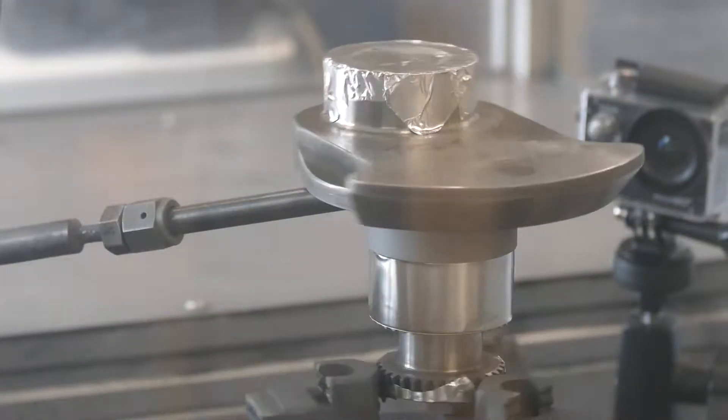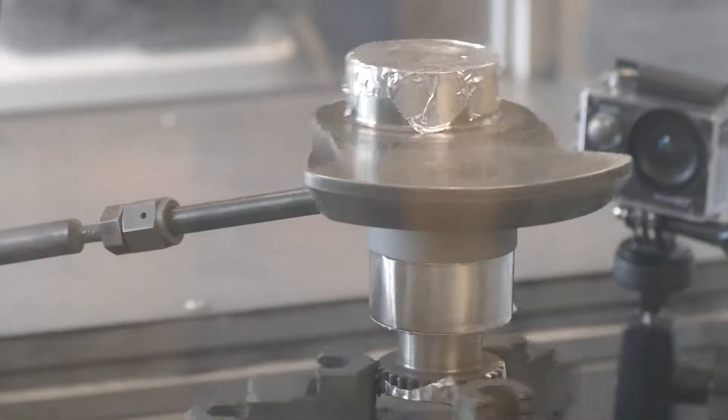In the case of the crankshaft, the worn bearing surface was machined down just enough to remove the surface damage, approximately five thousandths of an inch.